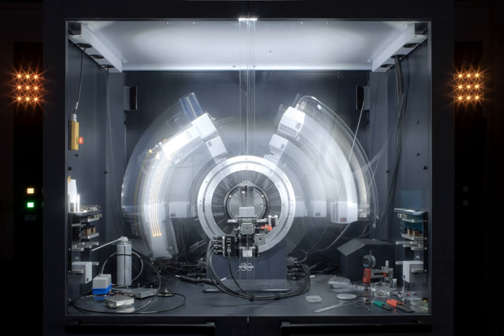Using synchrotron radiation frequently has specific requirements for X-ray crystallography. The intense ionizing radiation can cause radiation damage to samples, particularly macromolecular crystals. Cryocrystallography protects the sample from radiation damage by freezing the crystal at liquid nitrogen temperatures, approximately 100 K. However, synchrotron radiation frequently has the advantage of user-selectable wavelengths, allowing for anomalous scattering experiments which maximize anomalous signal. This is critical in experiments such as SAD and MAD.